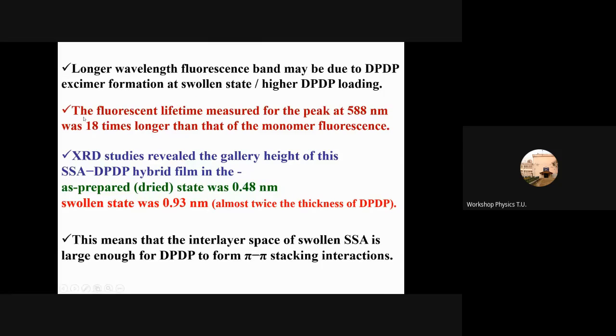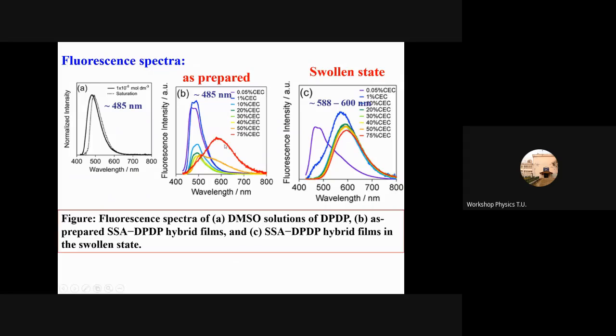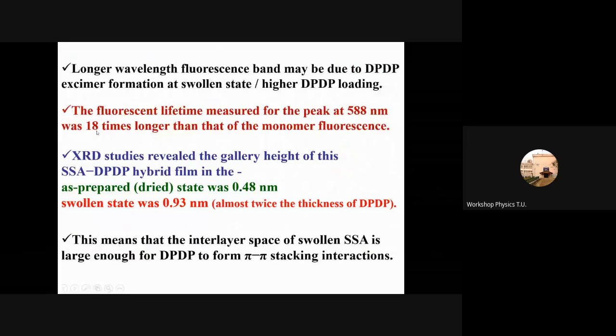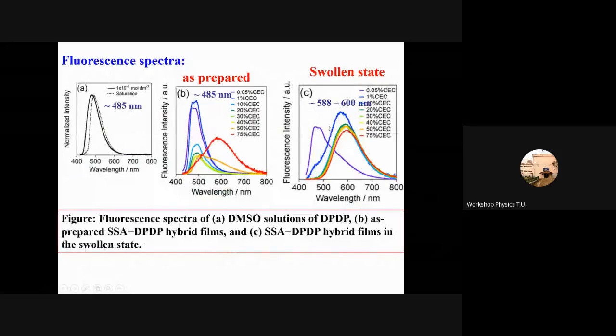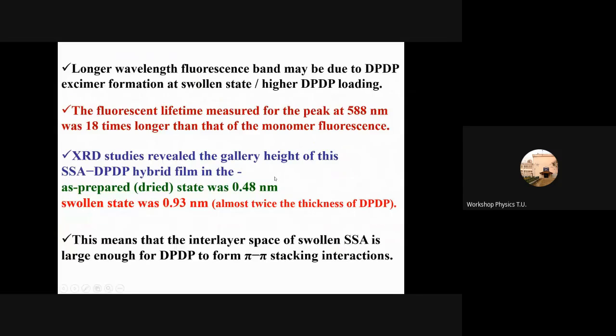So to have more idea, we did lifetime measurement also. And we have seen that this longer wavelength, broad structureless band of the swollen film has almost 18 times longer lifetime than the as-prepared film fluorescence band. Mainly the excimer band has a longer lifetime. Again, we studied XRD, and from XRD, for the as-prepared film the gallery height was 0.48 nanometer, but in the swollen film it was 0.93 nanometer. So this is almost double that of the normal film. From this, we conclude that in the swollen film, two pyridinium molecules stack together and form an excimer through pi-pi stacking. Accordingly, it shows this longer wavelength band in the fluorescence spectra.